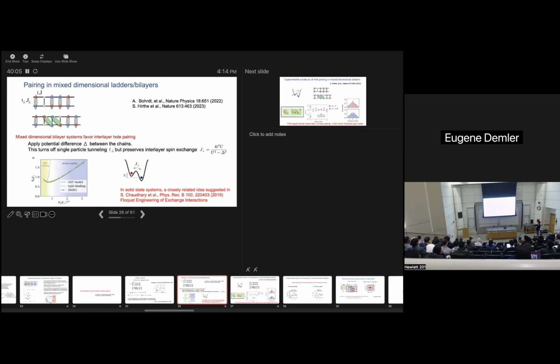On the other hand, now if we think about this kind of virtual tunneling impact, the energy of the intermediate state is no longer this repulsive energy U, but U minus delta. And that's why having this bias actually makes the exchange interaction larger. Therefore, this approach actually achieves two things. It switches off single particle tunneling T-probe and it boosts J-probe, which is exactly what Morris Rice and company wanted to do in their model.